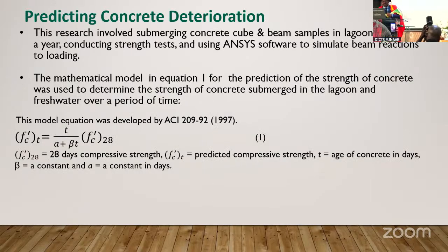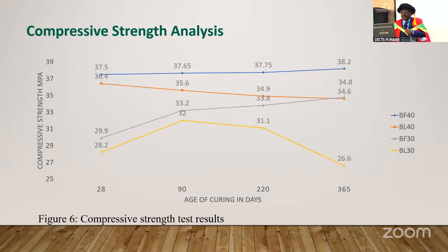Now, to predict the deterioration, this research involves submerging concrete cube and beam samples in lagoon water for a period of 1 year, conducting strength tests, and using ANSYS, a software to simulate beam reaction to loading. The mathematical model in equation 1 for the prediction of the strength of concrete was used to determine the strength of concrete submerged in lagoon water and fresh water over a period of time. This model equation was developed by ACI 209.2R. The results.